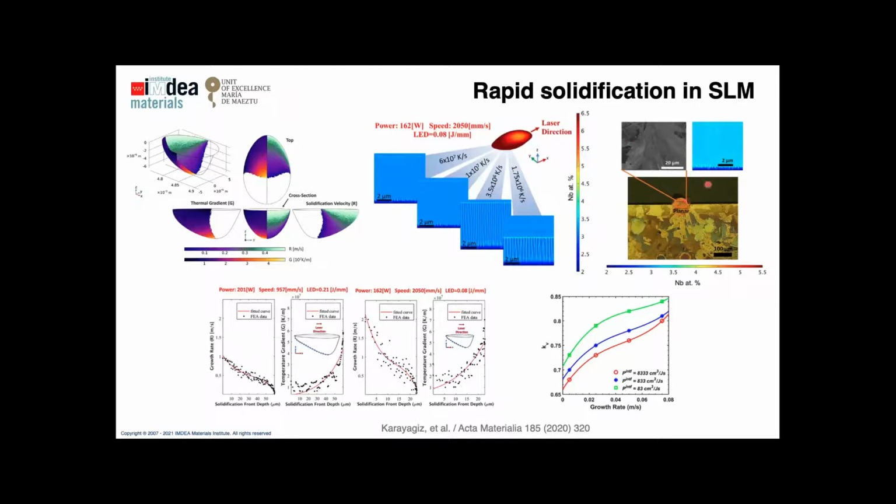For instance, in the case that they have planar, they calibrate somewhat the parameters that they're missing, like the permeability, to look at that. And two things that stand out from the study to me, one was already mentioned by Charles-André. That is the evolution of the growth rate and the temperature gradient within the melt pool. So if you go from the tail to the bottom here, you see that the growth rate for the scan speed of 1 meter per second goes from 1 meter per second, but it drops to 0 at the bottom of the melt pool. And the temperature gradient evolves like this too.